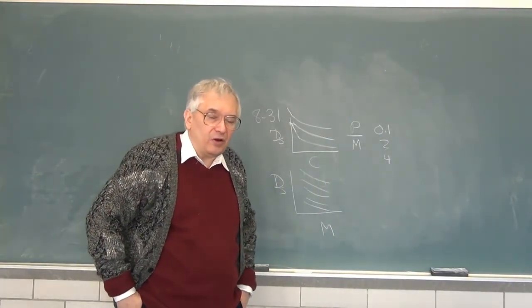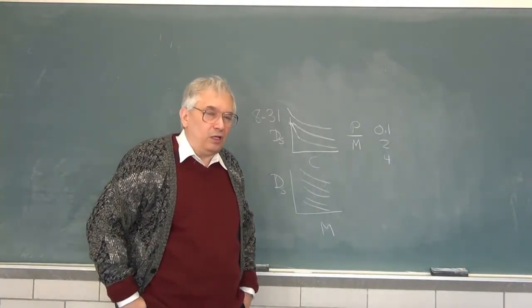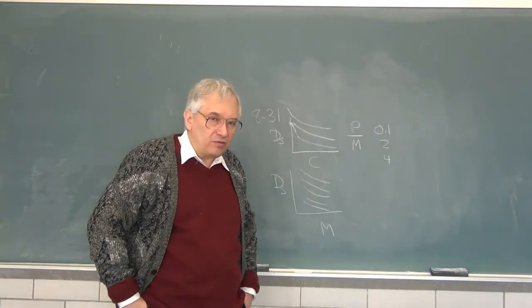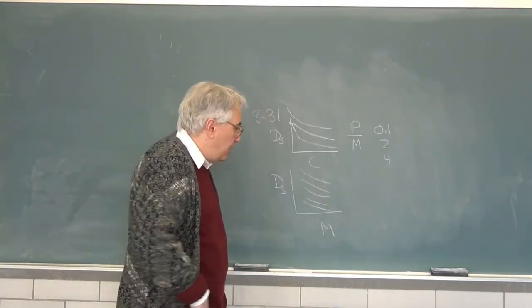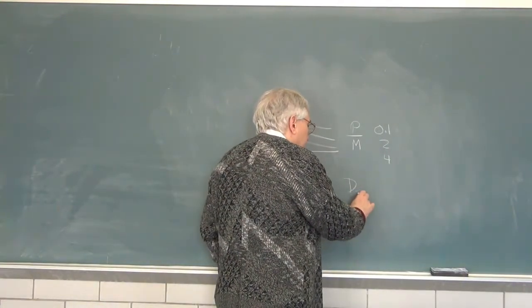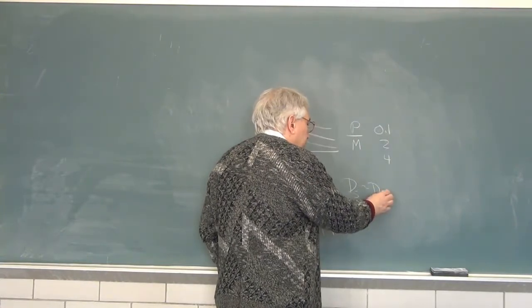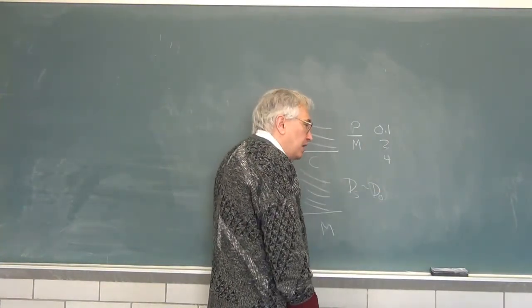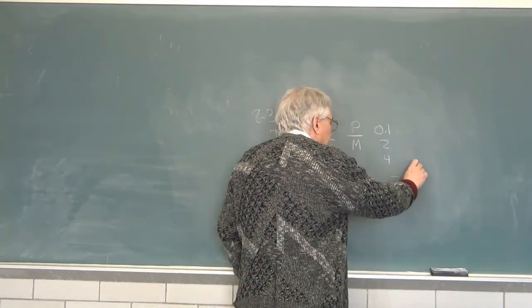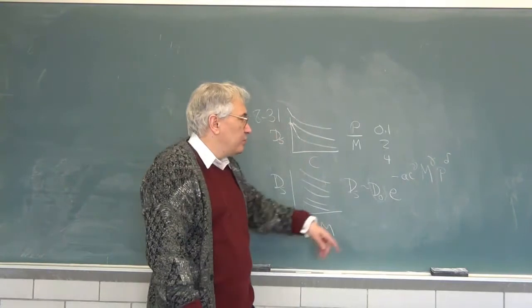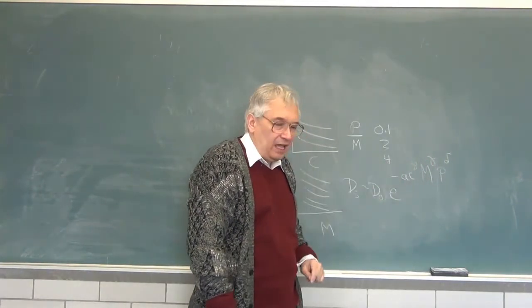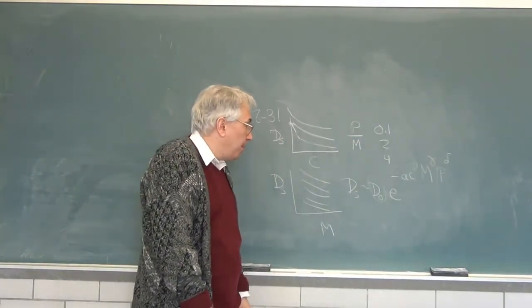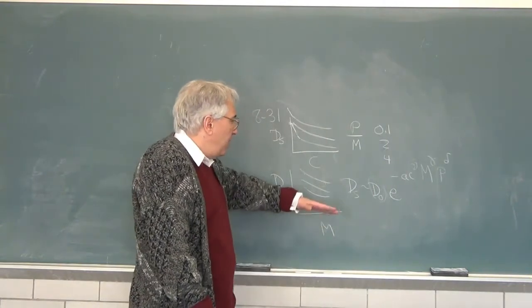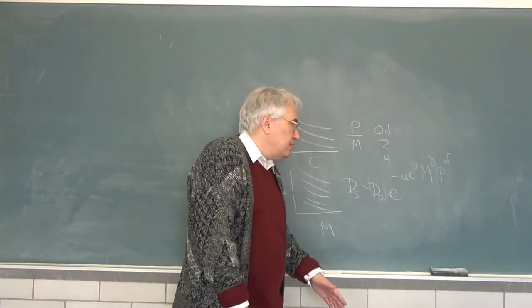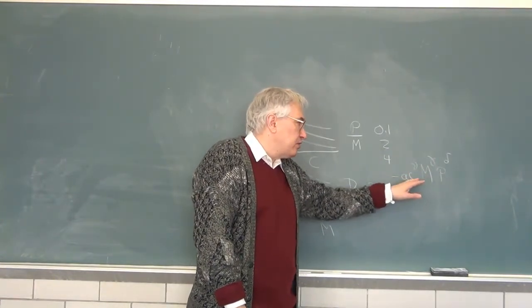However, what you see in the two figures, parts A and B, are in fact one surface. You see eight curves, but the eight curves are not independent from each other. Instead, we had a fitting function, DS is D0, and we have to take into account the fact that as you change the probe size, D0 changes, e to the minus a, c to the nu, M to the gamma, P to the delta. We generate a family of curves using single values of delta, gamma, nu, and a. So there are actually only four parameters, plus D0, which you can measure separately. And all eight curves are eight separate slices through the multidimensional sheet described by this function.